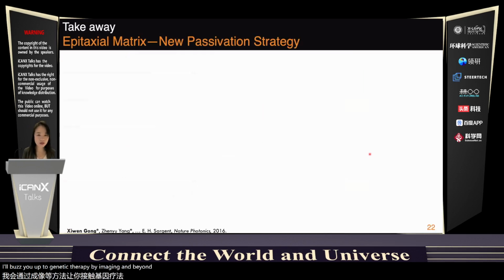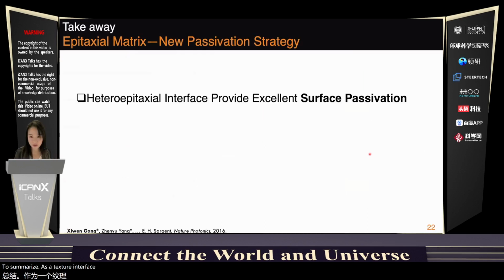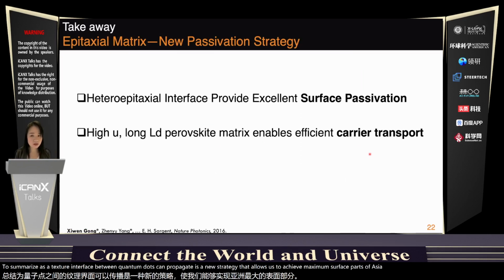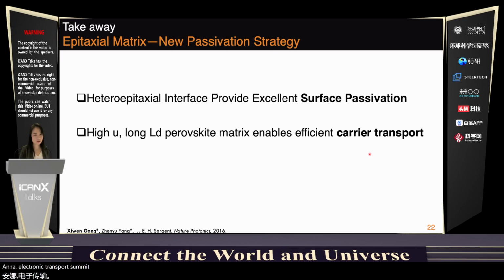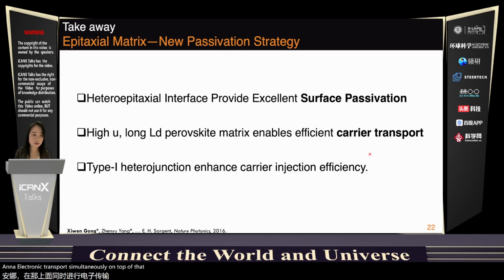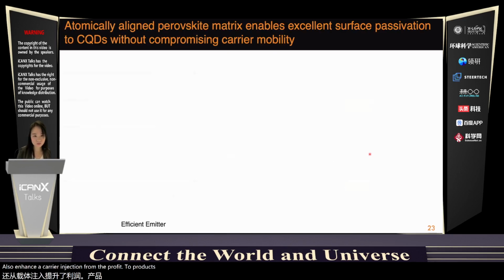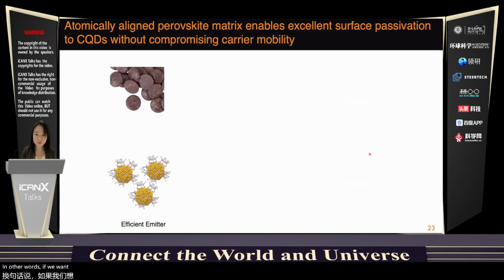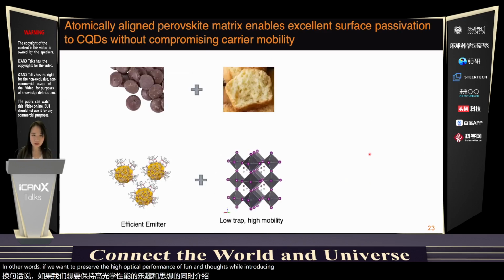To summarize, the epitaxial interface between quantum dots and perovskite is a new strategy that allows us to achieve excellent surface passivation and electronic transport simultaneously. On top of that, this type 1 heterojunction also enhances the carrier injection from the perovskite to quantum dots. In other words, if we want to preserve the high optical performance of quantum dots while introducing a new flavor of electronic transport, we need to find the right path to incorporate them.